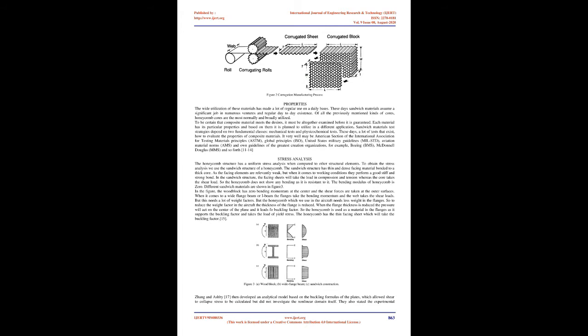First, the foil sheets are applied with a corrosion resistant coating and then adhesive lines are printed on the sheets for the expansion process. Then the honeycomb block is cut into required thickness slices and then expanded to a certain elasticity. Whereas in the non-metallic core, after the expansion it is placed in the rack and then dipped in the resin, which is hot set in the oven. The dipping cycle is repeated until the desired density is obtained. Generally the dipping cycle will be 3 to 4 cycles.